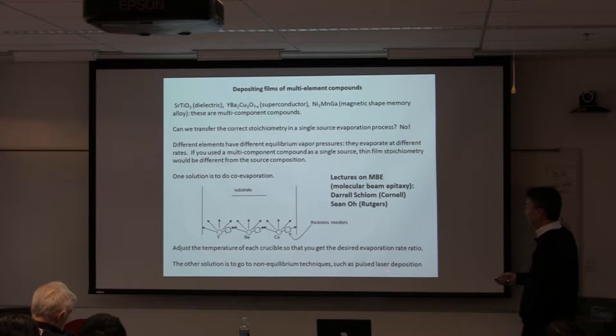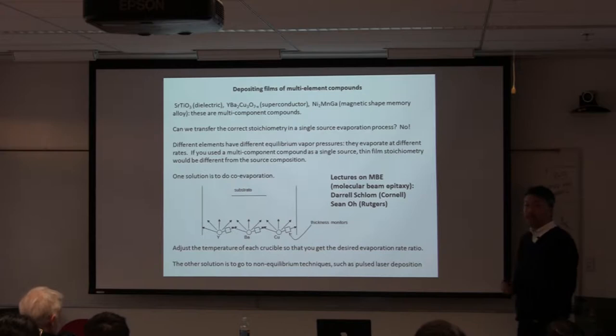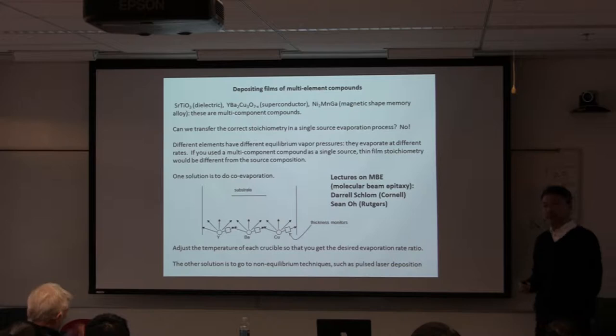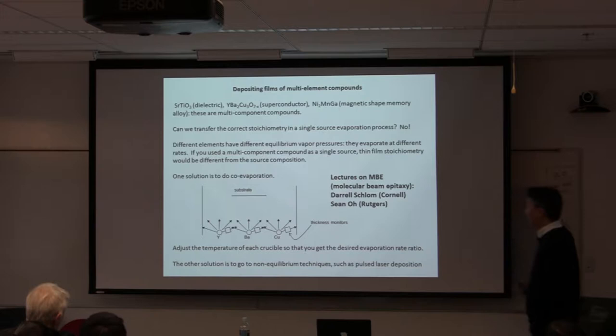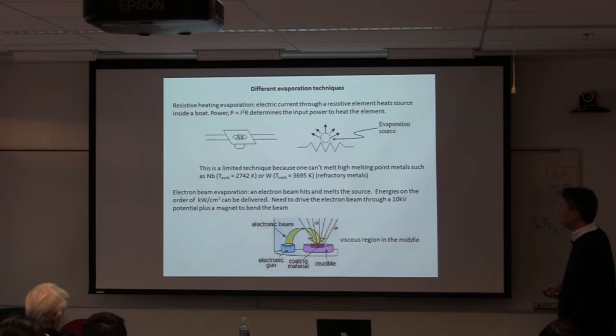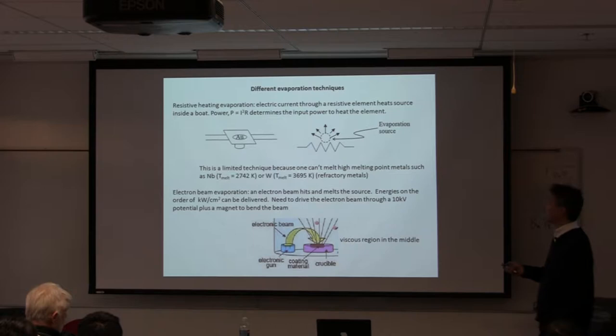One big difference with PLD is that it's a non-equilibrium technique. Non-equilibrium sounds bad, but in this instance it helps, because it means you get stoichiometric transfer. PLD delivers laser power to the target in a really short period of time, resulting in instantaneous evaporation and a non-equilibrium process.